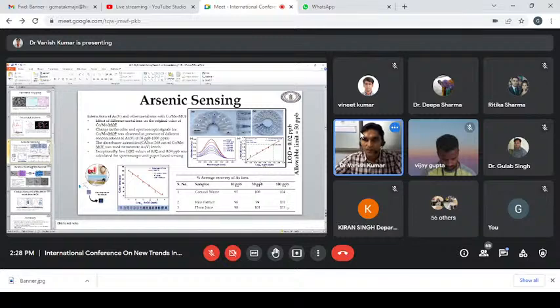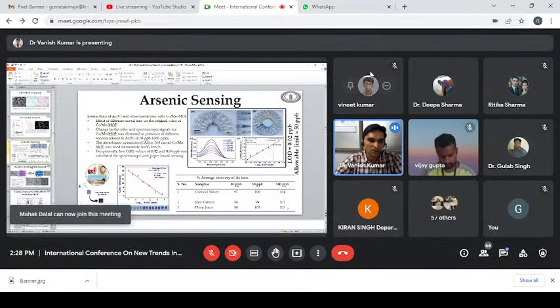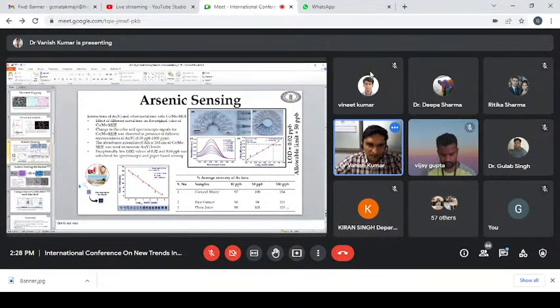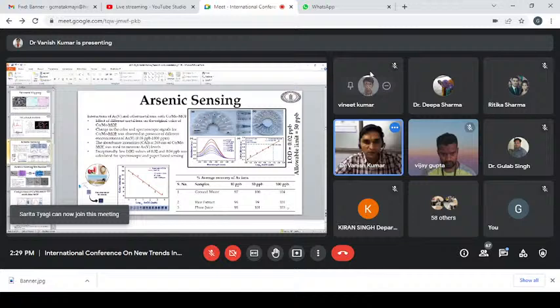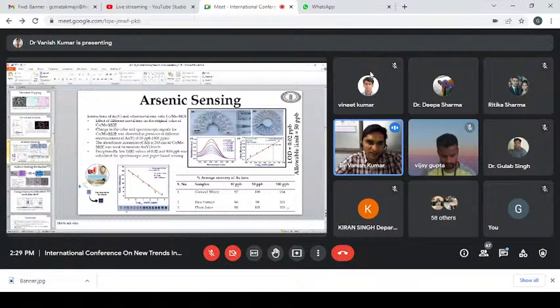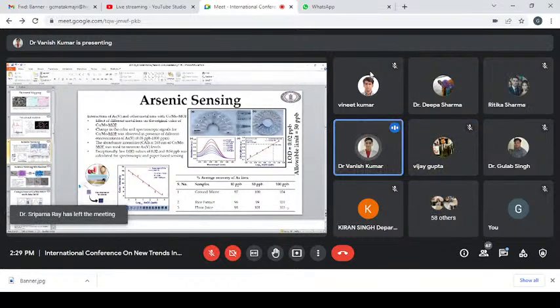So after that, we developed a paper sensor using this material. We soaked a paper, Whatman paper or simple filter paper, cellulose paper, with this material, and these are the sensor strips. They are only around 1 centimeter by 1 centimeter, or even less than this, used for fabrication of this sensor. And we soaked around 1 mg per ml of MOF onto this strip, and this is again of purple color. After addition of arsenic, the color of this strip was also changed from purple to blue.